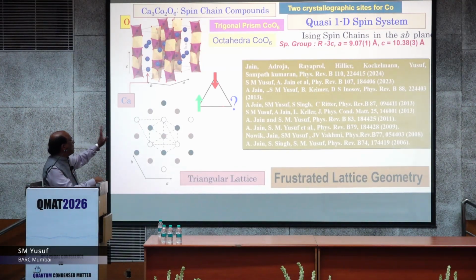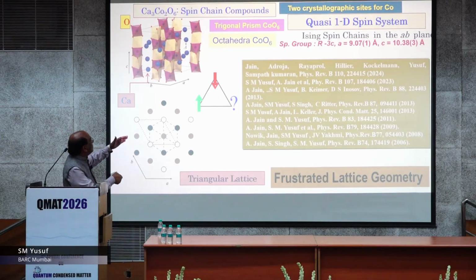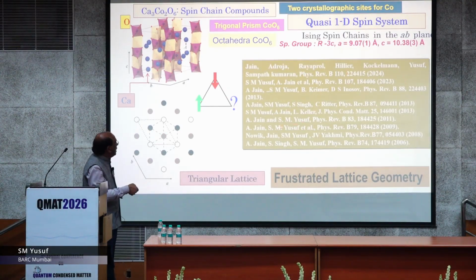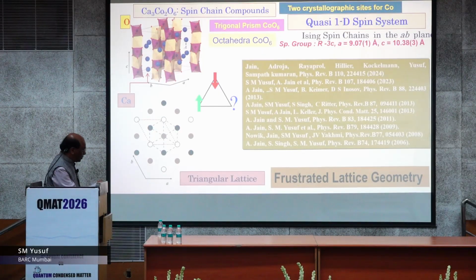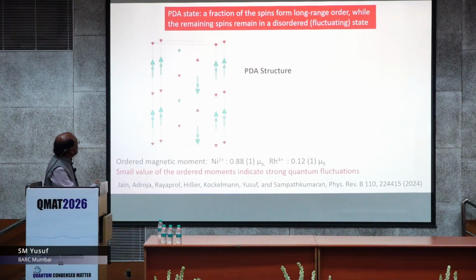So what I just said, the triangular lattice, here it is a real system example, how the triangular arrangement is seen in a real material where with antiferromagnetic exchange interaction, and this third spin needs to be frustrated by this definition, and we have worked, and let me give one or two slides from this kind of work. So for example, when you say this kind of frustrated system with the triangular, what happens out of three spins, the one spin which is at one vertex of this triangle, it is not ordered. So this is called partially disordered antiferromagnetic structure. That is the structure. This is a disorder.